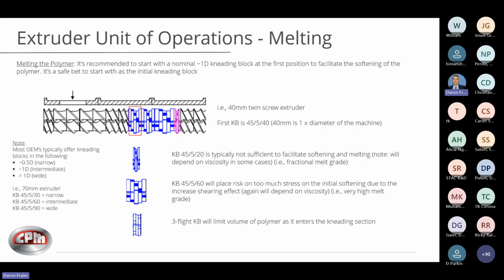But say, for example, a 45/5/20, because it's so narrow, remember it's primarily distributive, it's not capturing a lot of that polymer in the lobe between the lobe tip and the barrel wall. So it doesn't have a lot of dispersive or impart a lot of shear stress.